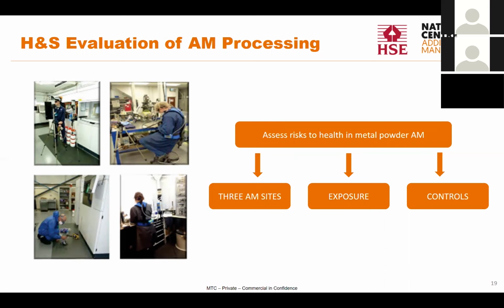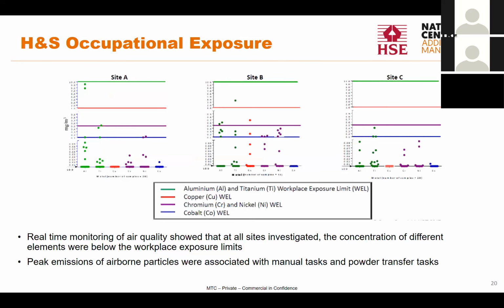So effectively, the HSE came into these three sites, and we put various testing equipment around the lab. We would put sticky tabs at different locations from an activity. The operatives themselves had personal monitors close to their mouth and close to where their respiratory equipment would be pulling air from if they were wearing belts. So we could get an indication of the level of particulate exposure at those locations. And then we also did personal monitoring. We did some testing of the operatives' urine to see if they had elevated levels of materials that they use in AM. And so these are effectively the results for the 3 sites.